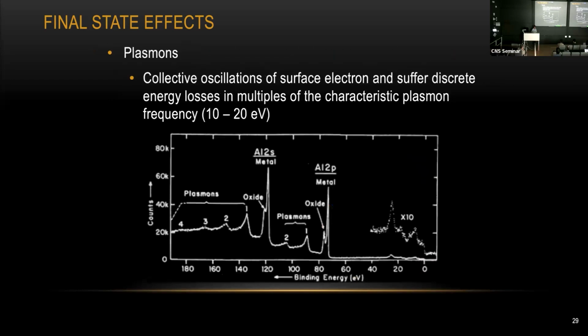And the very final state event we are going to discuss today is called the plasmon. It mostly happens only for materials like aluminum or magnesium, and if the surface is really clean, when you do the measurement, you might see some additional peak right here. For instance, this is an aluminum 2s peak, and that's an aluminum 2p signal right here. But you can see next to this main peak, there's a series of smaller shoulder peaks with the same energy separation, for aluminum around 15 eV. All these additional plasmon peaks are not very useful. Just for your information, you might see them if you're working on a very clean aluminum sample surface.